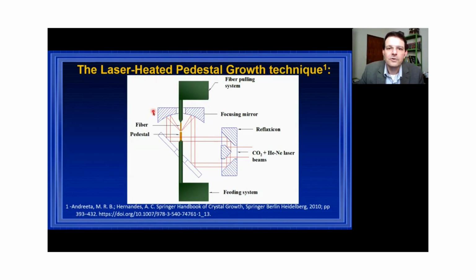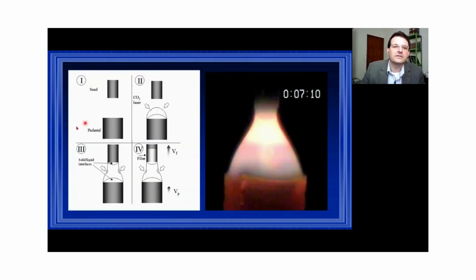Then you can reflect and direct the laser to a focusing mirror, and this will lead to a ring-shaped focus on the surface of the material that you would like to melt. So these are the steps. You have the mechanical alignment of a seed and a pedestal. The pedestal is the material that you would like to melt, okay? And then you can create a small volume of molten material on the top of the pedestal. Then you can touch the seed to this melt, and now you have a liquid phase that is kept glued to the solid phase by surface tension, and you don't have crucibles here. So you can reach any temperature possible for this compound, okay?